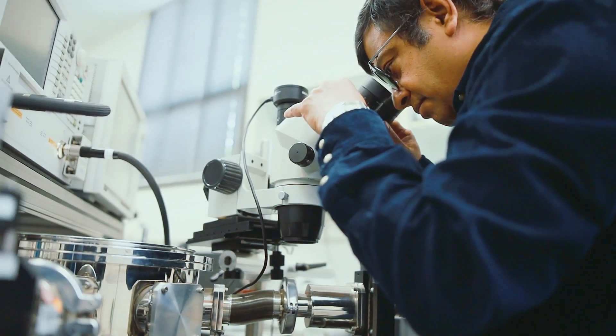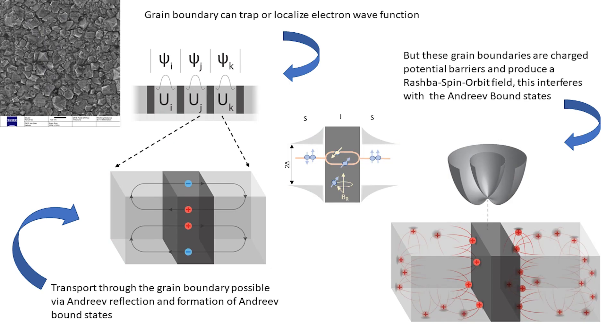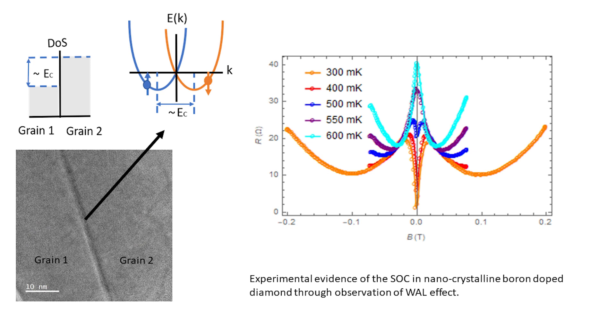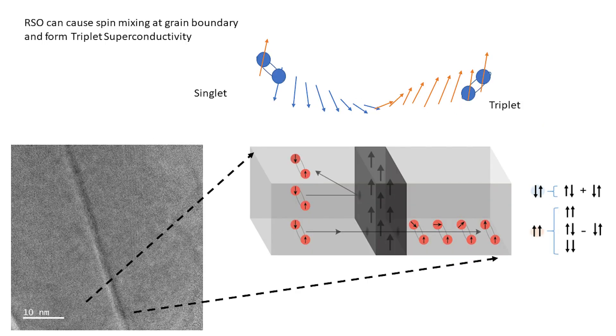This is possible because we have seen a particular structure which is called grain boundary structure of diamond, which is boron-doped and shows a very distinct superconducting transition at 4 Kelvin. This transition is explained by Andreev tunneling through the grain boundary of diamond, which acts as a potential barrier and gives an effect which is called spin-orbit coupling. This is the reason we can see a new kind of superconductivity, which is called spin triplet superconductivity, which is first time observed in diamond.